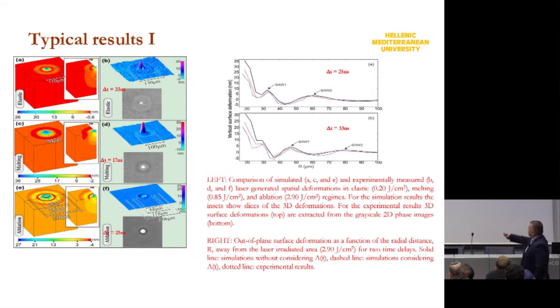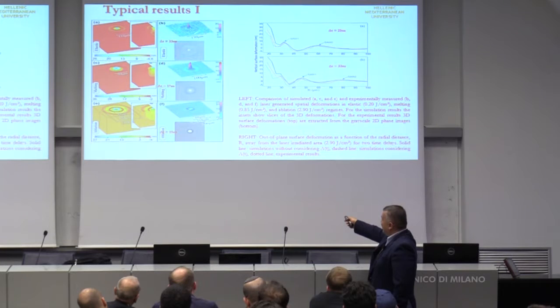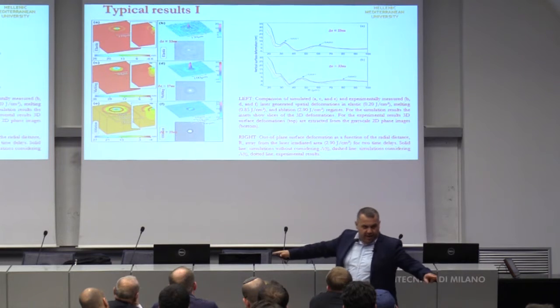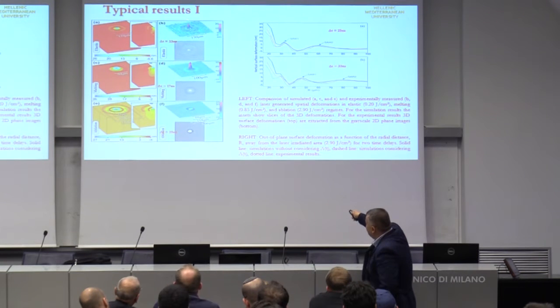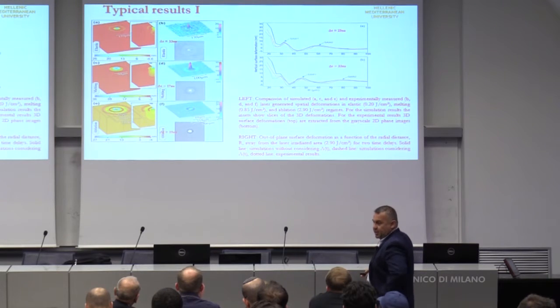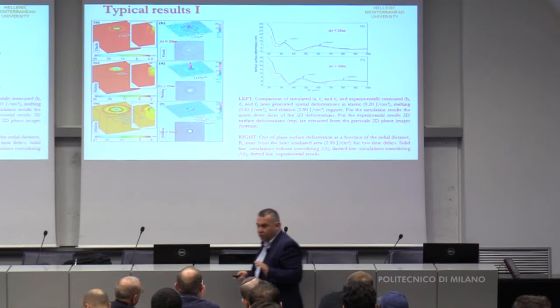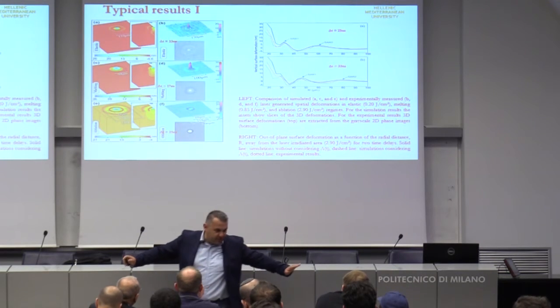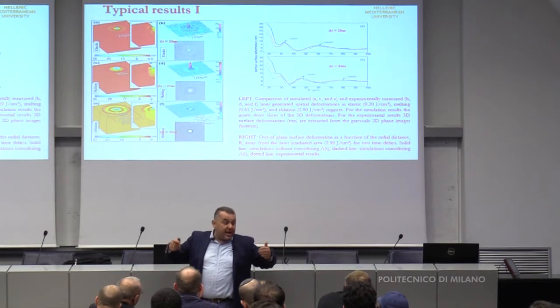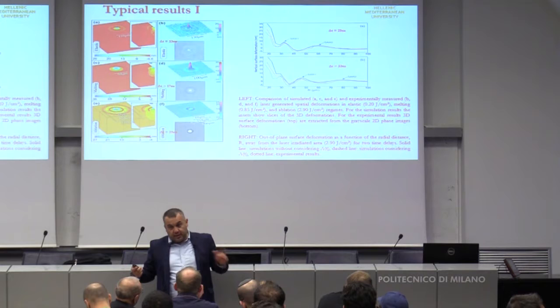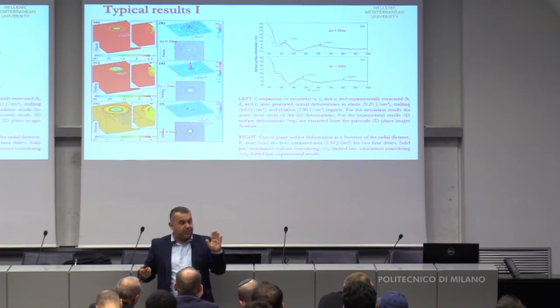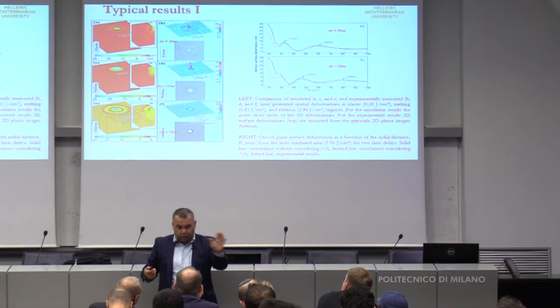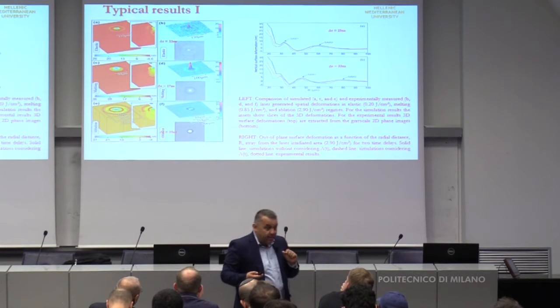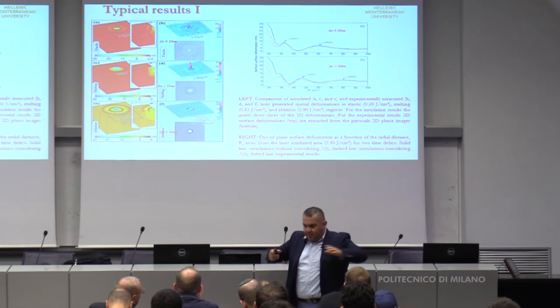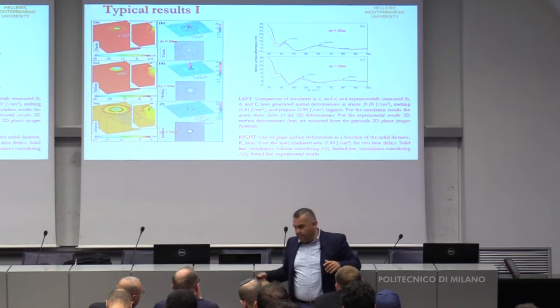Let's see some typical results. Here is the theory, and here is the experiment. Here is a real picture of the surface, 200 microns, but you can see that this kind of surface waves is in the order of nanometers. Yet we can actually do cinematography of the Rayleigh waves of the surface at any time delay after the excitation that we want. Each experiment is one time, then we have to change position, and we are able to observe nanometer waves of an area that is many micrometers.